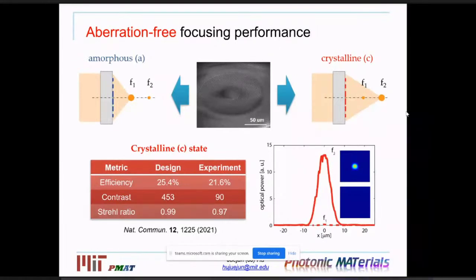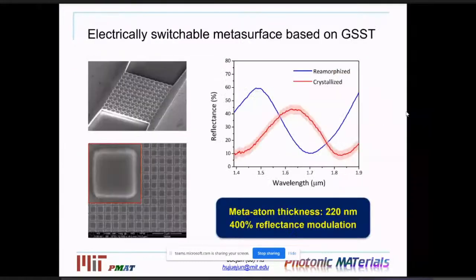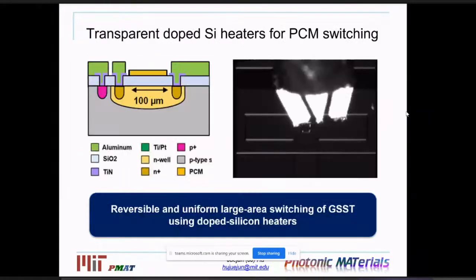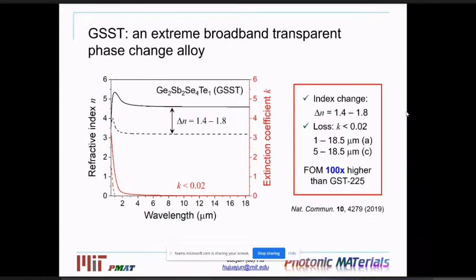Okay, thank you. And another quick question: in the transparent doped silicon heater, you showed the contrast was changing. What is the time scale of that change? Okay, good question. It depends a bit on the material. If you are talking about GSST, which is the material we use here, typically we use about millisecond pulses. The fastest switching speed we realized for crystallization is about 0.5 millisecond. For amorphization, it's much quicker. We can do it within a few microseconds.